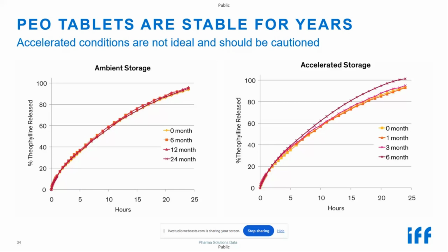6, 12, and 24 months. And then tested for dissolution at those time periods. And we see very good, almost identical release profiles when stored up to 2 years once it's in that compact. And that makes a lot of sense because you're reducing exposure to oxygen, because oxygen can't migrate into that tablet very easily. And so the rate of auto oxidation is going to go down.